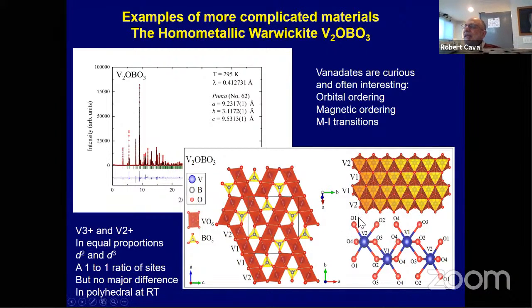And nominally, even though there are two kinds of vanadium, crystallographically two distinct vanadium sites in this crystal structure, they look the same at room temperature. So you get these partial chains of vanadium here. They have one kind of vanadium on the outside of the chain, another kind on the inside of the chain, but they're not very different. And when I see something like this, I think, oh, come on, they really have to be different somehow. So we did this high resolution synchrotron diffraction at room temperature.